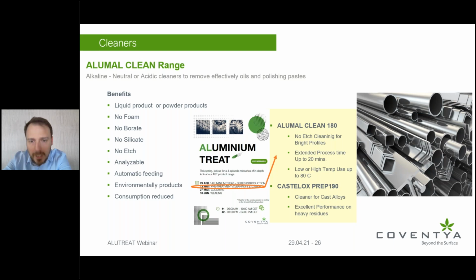And the second one is, because we also touch base with the difficult alloys or even secondary aluminum alloys, the Castelox Prep 190, a specifically designed chemistry that we are using for cast aluminum parts that are generally porous, and they have a lot of organic burned oils on the surface coming from the casting process. And it's an extremely durable and good chemistry in order to remove those residue components from the surface, in order to enable you to proceed with your successful operation.